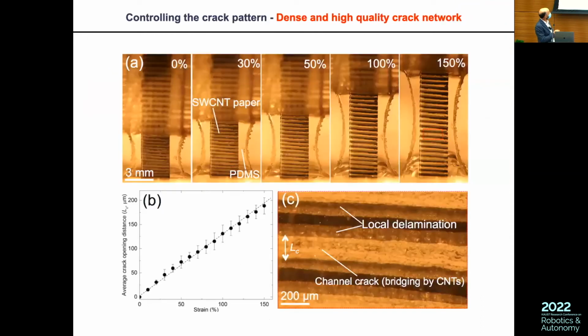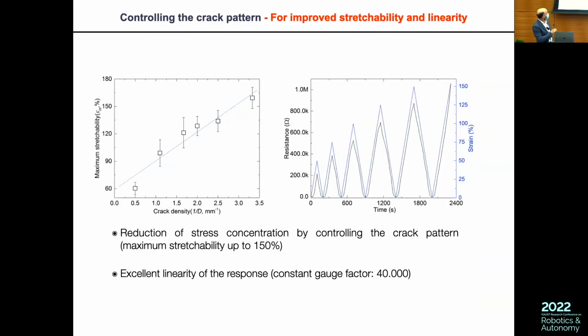And then when you do this, you get films where the cracks, you see, don't look the same at all, right? But you decide at the beginning where you put your cracks. So you can completely engineer this, and you can get a density of cracks that is much higher than the limit that you get with classical fracture mechanics, because you can initiate your cracks with a smaller step. And you can see that when you start to increase the number of cracks and the density of cracks, you can operate at levels of strain that are much higher. And here you go to levels of strain up to 100%. By doing this, you can reach a maximum stretchability on this system that goes up to 150%. And you get a very good linearity of your sensor.